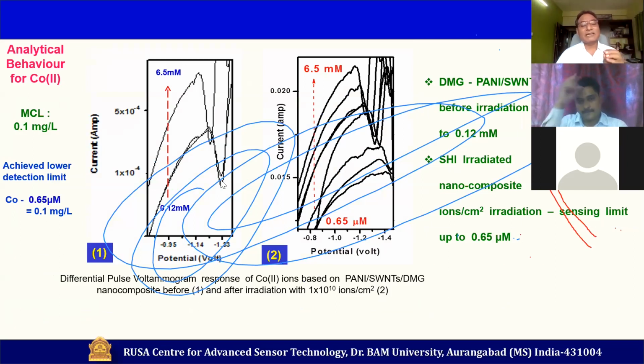Now, it was having a significant impact on the sensing. You can see before exposure, the low detection limit was 0.12. Whereas after exposure, the low detection limit reduced down to 0.65. It means that SHI irradiation has a significant impact on reducing the low detection limit. And you can see the MCL level is 0.1 and we could reach 0.1. So that was a happy moment for us.